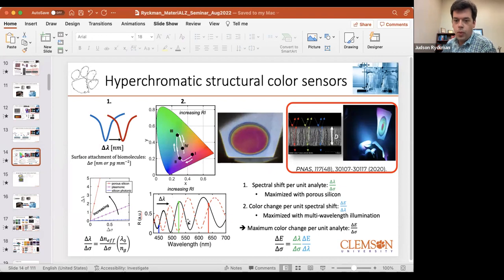Yeah. And do you find that the effective medium, are you just assuming the refractive index is the volume weighted average of the two components? Does that work quite well? So there's a slight modification. We use the Bruggeman effective medium theory. So there's a different equation that works well for interconnected networks. If you have sparse ones, there's Maxwell Garnett, but we pretty much use Bruggeman. Okay, right. Okay, thank you very much.